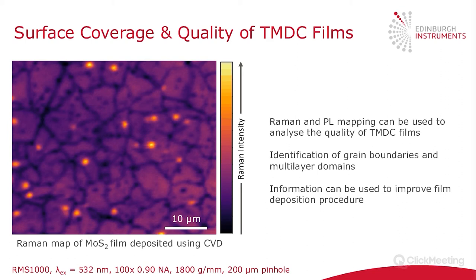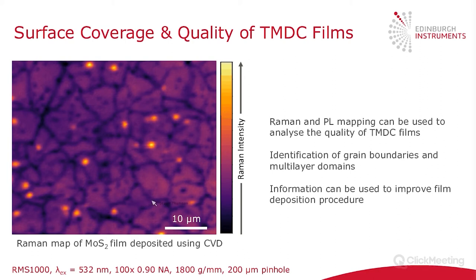You can also extend this to a much wider area. Looking at a continuous film of molybdenum sulphide deposited using chemical vapour deposition, the Raman intensity map can be used to analyze the quality of the MoS₂ film. Bright spots suggest multilayer MoS₂ present, and you can clearly see grain boundaries, giving an indication of how good the film is and whether the deposition procedure needs to be improved. 2D materials are a very important Raman application area, and next year we'll be doing a dedicated webinar on this topic.